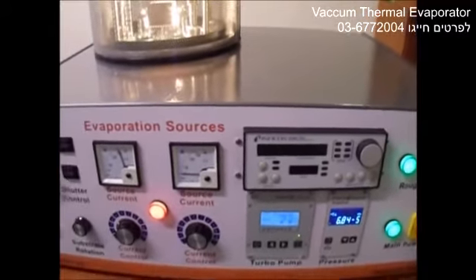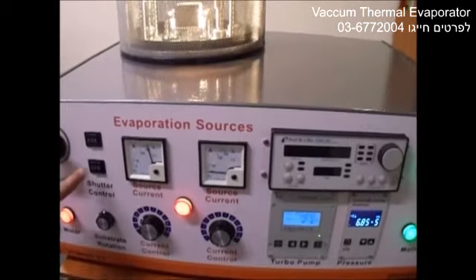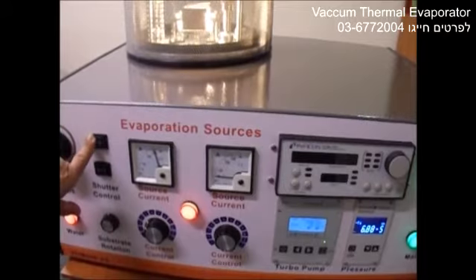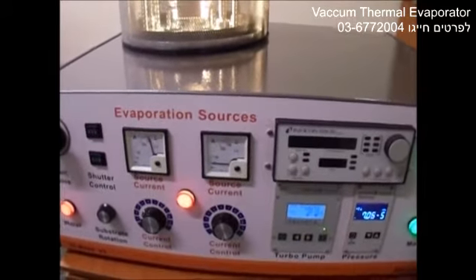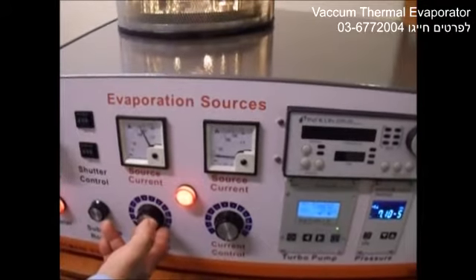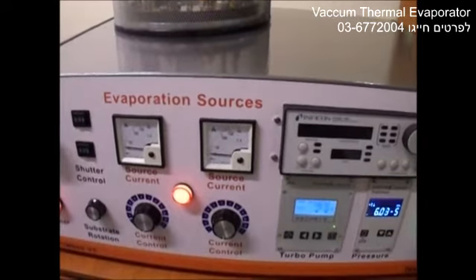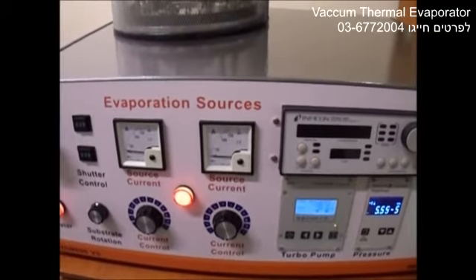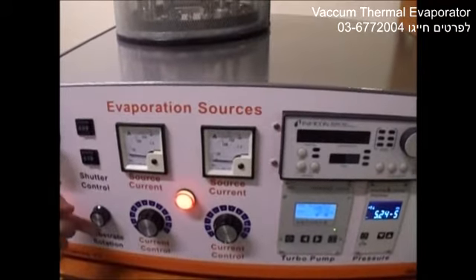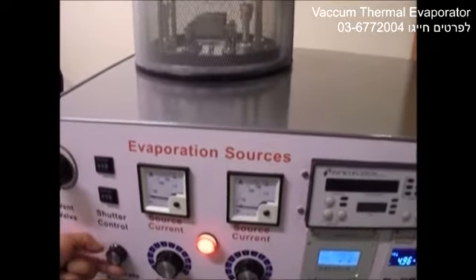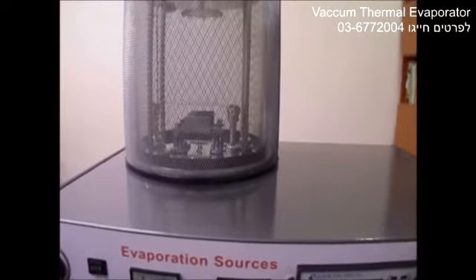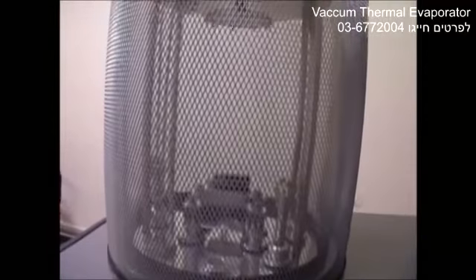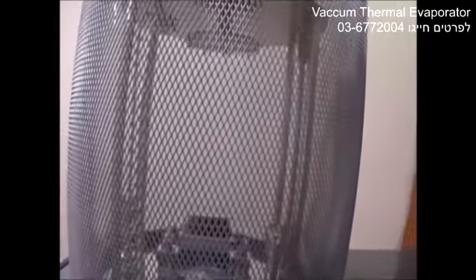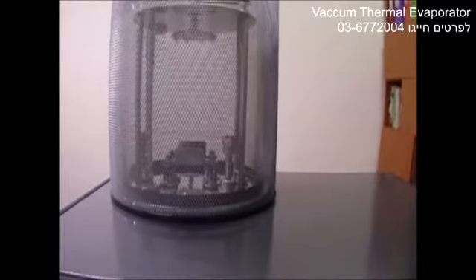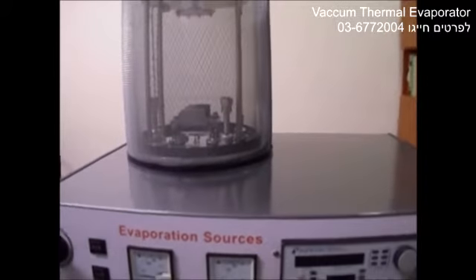As soon as the thickness reaches the desired level, we close the shutter, the deposition stops, and we minimize the current in the source. Of course, we can use the substrate rotation facility to improve the quality of the thin film that we produce on our sample. The thickness on our sample is measured through the quartz crystal head inside the sample chamber.